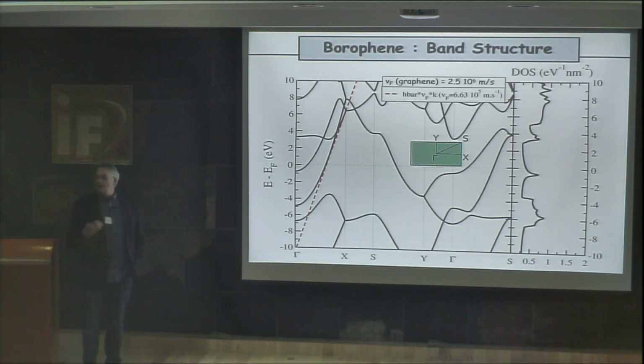So we have calculated the band structure using an ab initio technique, and you see that you have very strong dispersive bands which are crossing the Fermi energy, which is here. These bands are only present along the kx direction of this Brillouin zone, so along gamma-X, as you can see here, but also along Y-S, which is here, but not along, for example, gamma-Y or X-S. On X-S there is nothing, and on gamma-Y there is nothing as well. So you have a clear anisotropic behavior of this system from the electronic point of view. And so in fact this means that probably the transport will go only along the kx direction, but I will come back to this later.